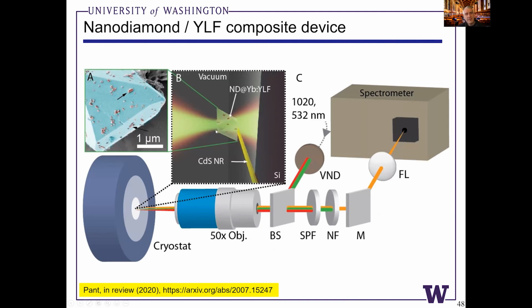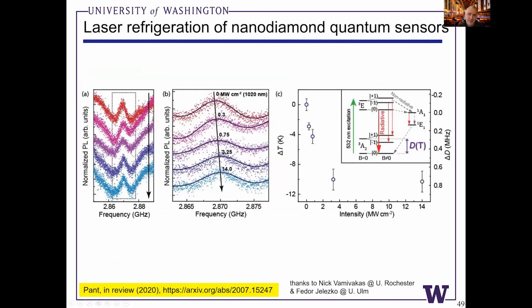So this ceramic is supported on a cantilever on a silicon wafer. We pump these diamonds in vacuum with a 1020 laser beam. This is how we pump the cooling. Then we have a secondary laser that we can pump to excite the NV center to do optically detected magnetic resonance. And so we're looking at this zero field splitting parameter, this D parameter. And I want to give a shout out of thanks to Nick Vamivakas at U Rochester, his group, and also Fedor Jelezko's lab at U Ulm, who have really helped us tremendously to understand and develop these ODMR measurements.